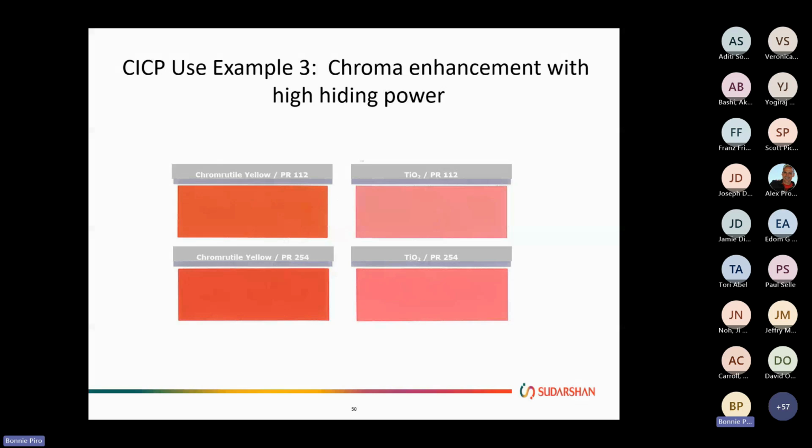Now, I will mention that in addition to these particular properties, you'll also have a weatherability improvement as well, especially with the red 254, which is a known organic pigment that has that TiO2 susceptibility for photodegradation. So swapping that out will get that property improved as well.